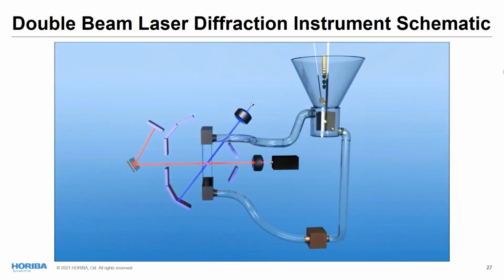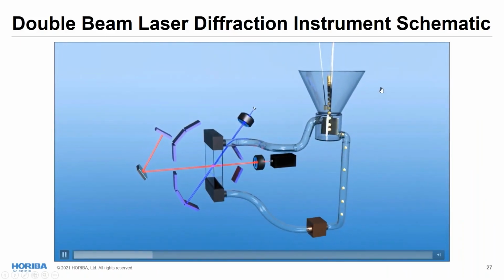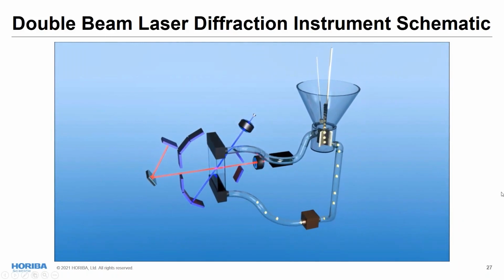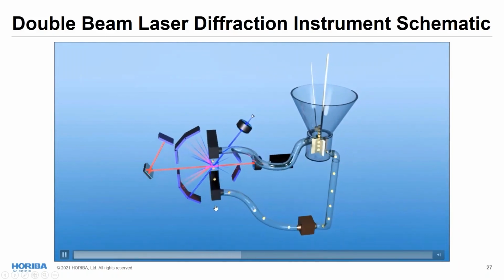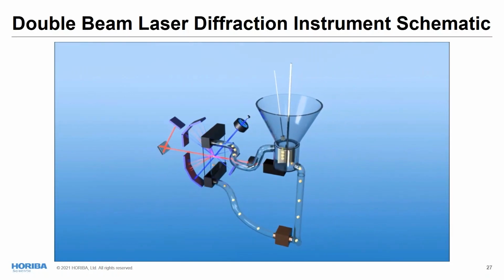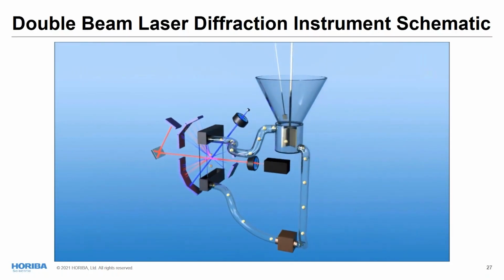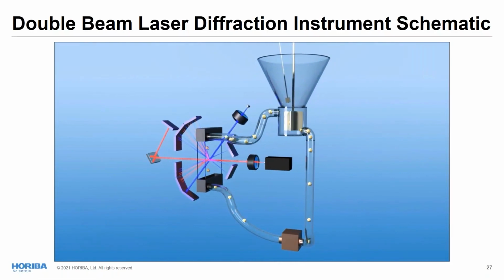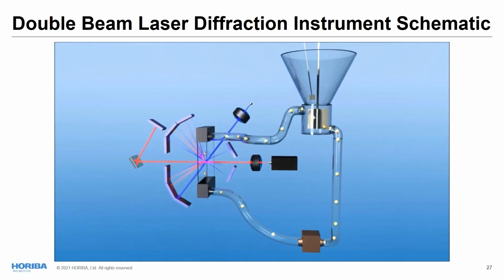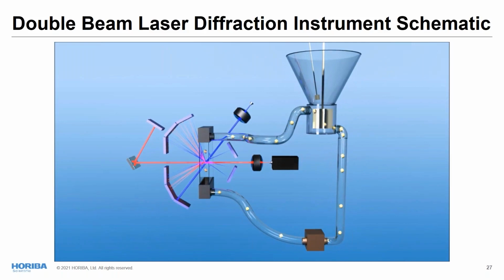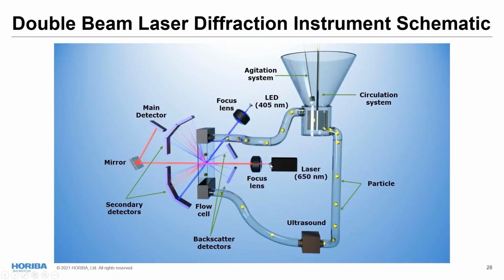The main concept of this technique is that you have your particles in suspension. In this case, we're using a suspension in liquid. When your particles pass through laser beams, they will scatter the light at multiple angles. All the intensities detected at different angles are used to calculate a diffraction pattern, which is unique for every particle size. In this case, I'm using the flow cell. I made this animation to show how exactly we did the studies that we're going to show, because that's the system we use for the metal powders.